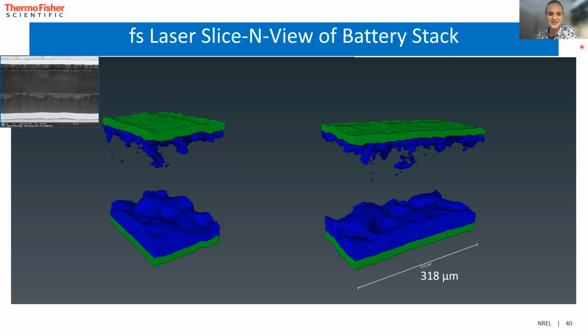Okay, last thing I want to say is that we can use the femtosecond laser to cross-section mill and image, which then we can create these 3D volumes, and we can understand the topography of the lithium and look at dead lithium as it exists. Because some questions you have when you look at a cut face is, okay, is it still connected, even though there's a lithium grain that's way down closer to the separator, maybe there's still a network that connects it up. And so from this slice and view imaging, we're actually able to get evidence of if the lithium's dead and disconnected or if it has pathways.